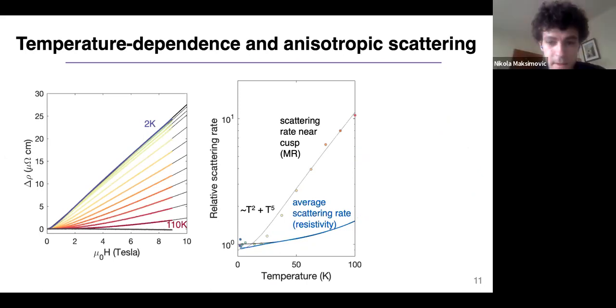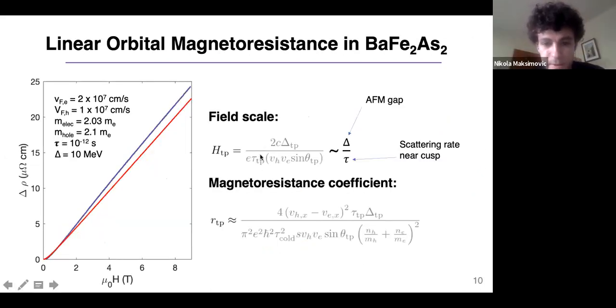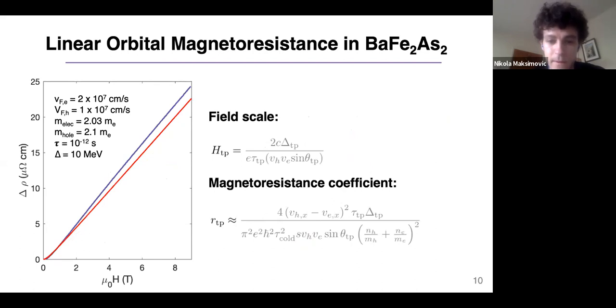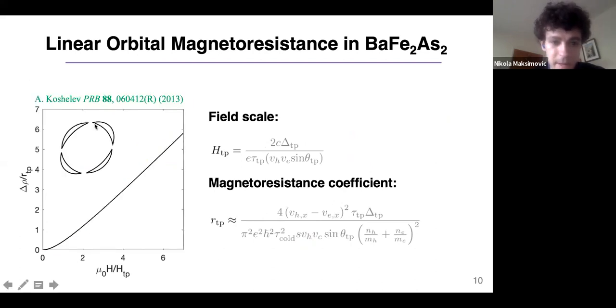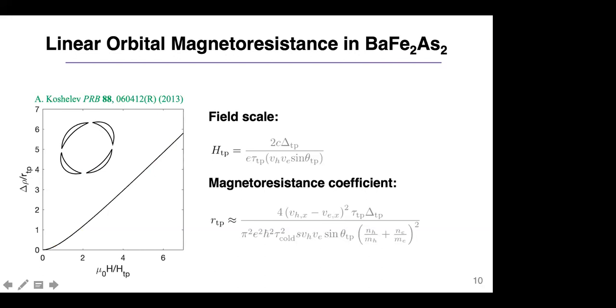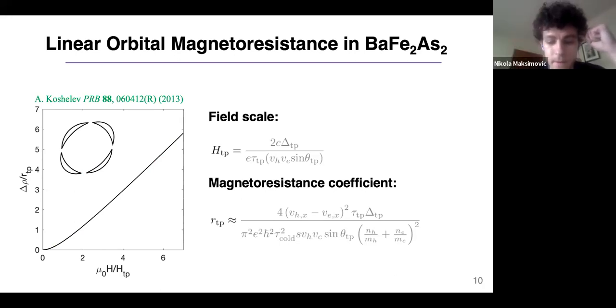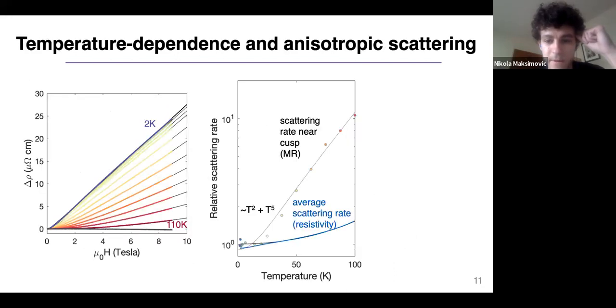Yeah, so these parameters depend on the scattering rate, primarily the scattering rate in the vicinity of that turning point. So this model is the magnetoresistance only of this region, which may not have the same scattering rate as the rest of the Fermi surface. The gap may change, that's correct. So that is not taken into account in this plot right here. Yeah, that's a good point.